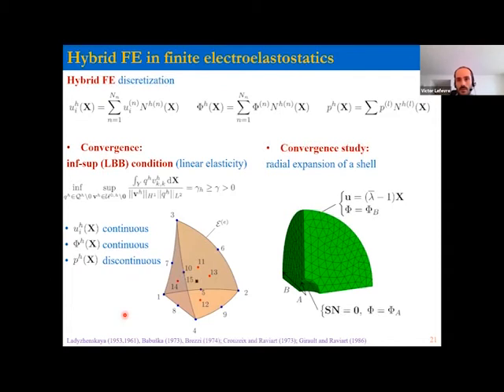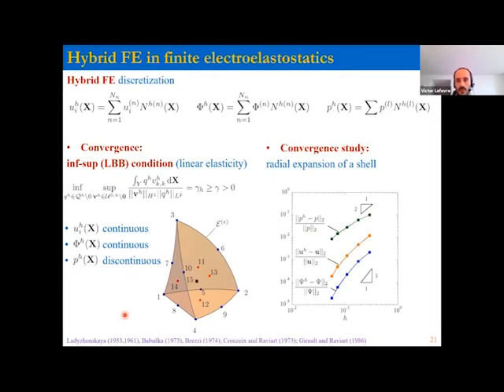So what we did was a convergence study. We looked at the famous problem, the radial expansion of a shell, which you can work out the analytical expression. And once you have the analytical expression, you can do a convergence study and check that you have the good convergence rates. So 3 for the errors in the L2 norm for the displacement and the potential, and 2 for the L2 norm of the error in the pressure.